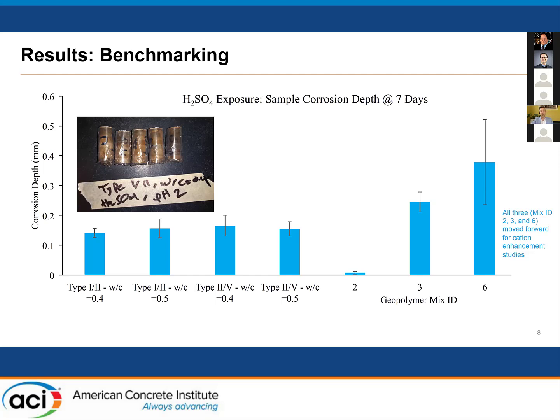But in terms of the geopolymer cements, you can see that formulation number 2 exhibited the best performance in the sulfuric acid testing. And it's clear from this result how much better low calcium geopolymers can be at resisting sulfuric acid attack.